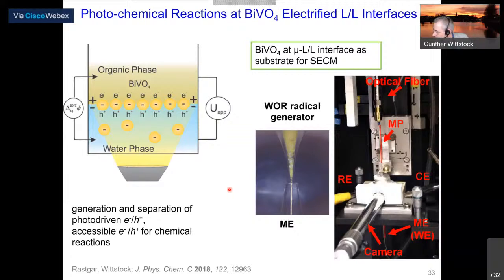Maybe I go to the next one, and that says, in the first part of your lecture, how to put the metal oxides in the ultra microelectrode. Yes, the cavity microelectrodes we fill by having the powder, let's say on a mortar, and then we just gently dip in the cavity microelectrode and press a little bit. So it's just filled by knocking into the powder. It's actually very easy. And then we also remove it by exposing it to an ultrasonic bath in ethanol or something, and then the particles fall out again. That has actually not turned out to be so difficult.